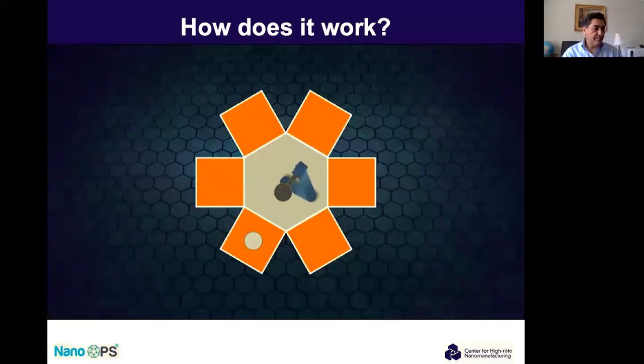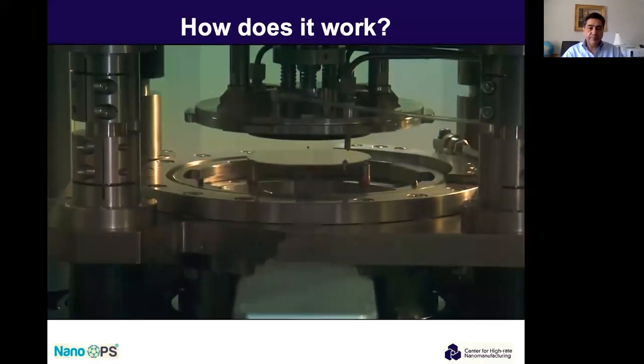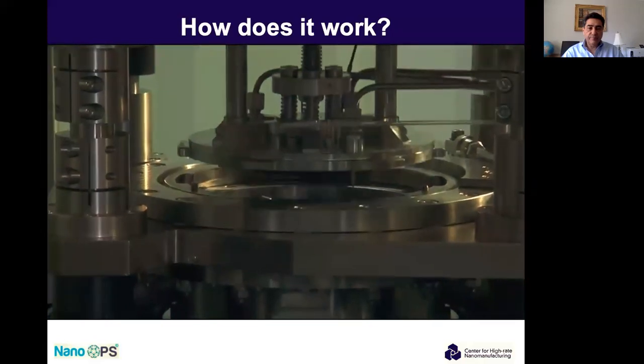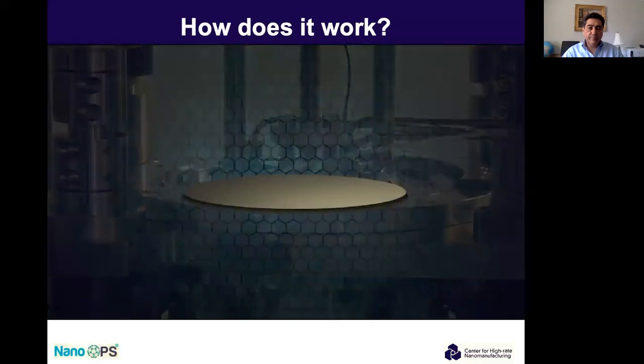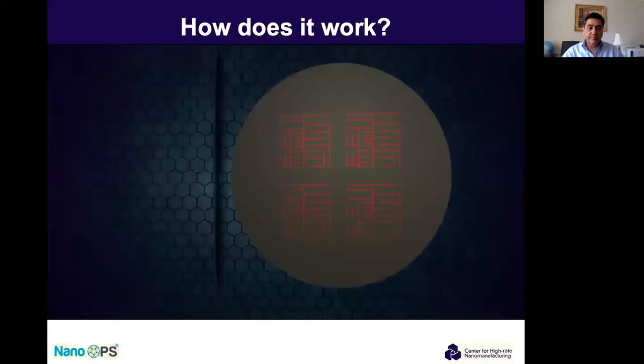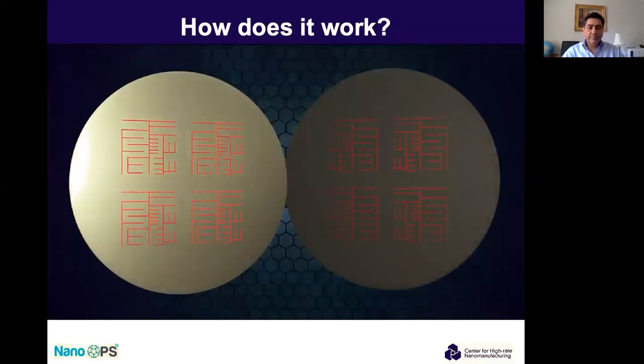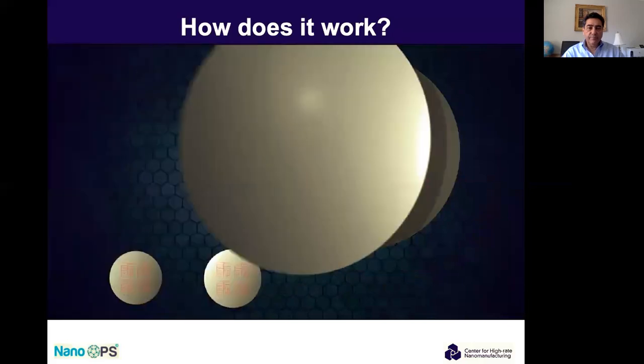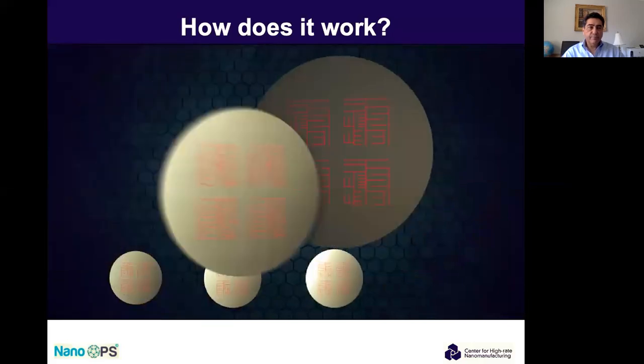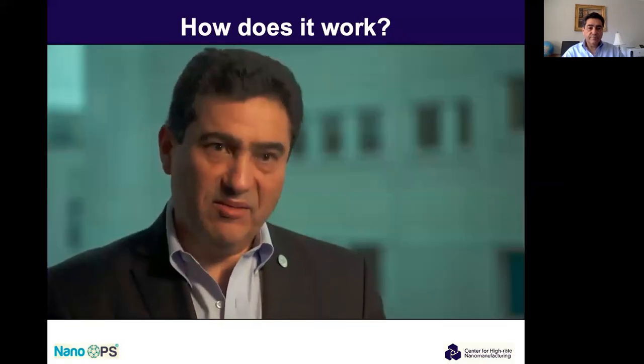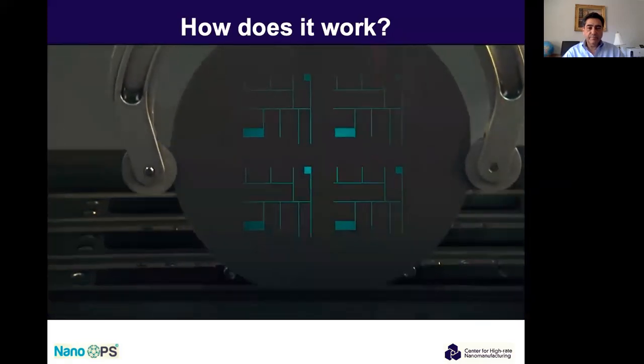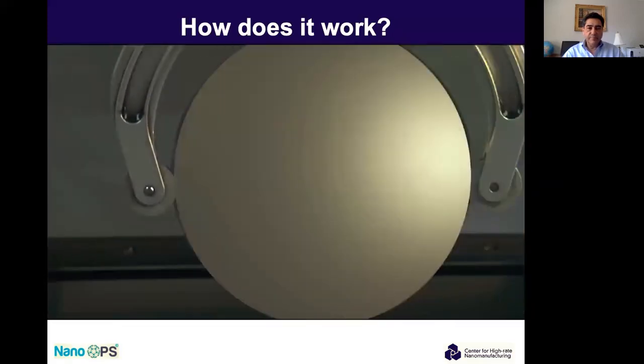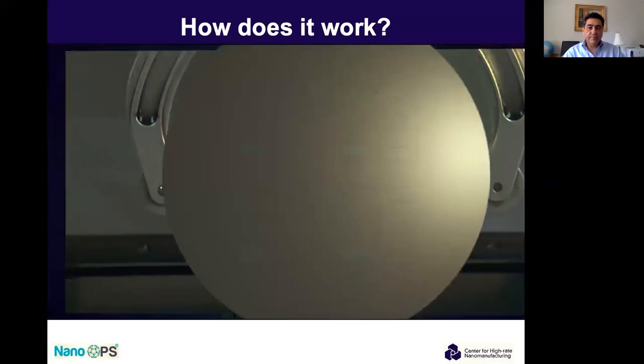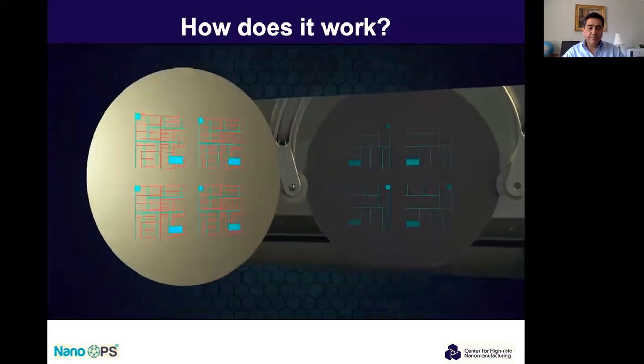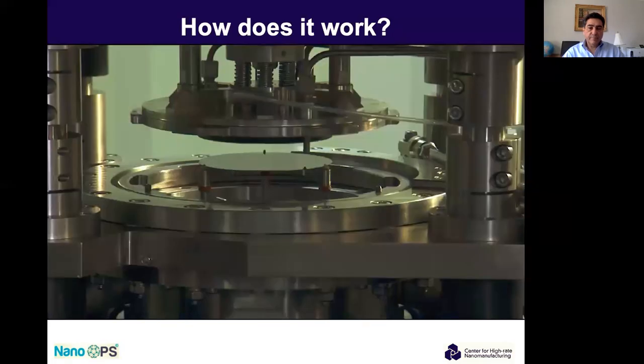The newly inked template is aligned to the blank wafer, and both are taken to the transfer module, where a pressure device presses the two together. In an instant, the pattern that was inked on the template is printed onto the wafer. And like a printing press, the process can be repeated to make as many wafers as you want from the same template. We can use that template thousands of times. Additional layers of circuitry can be added by inking a new template with a different pattern and pressing it against the existing wafers to make more complex electronics. The entire process takes minutes compared to hours in a traditional chip factory.